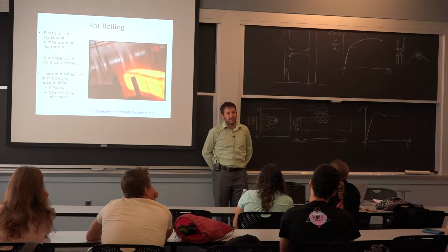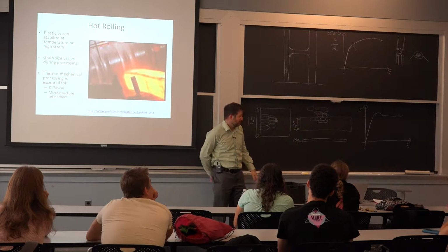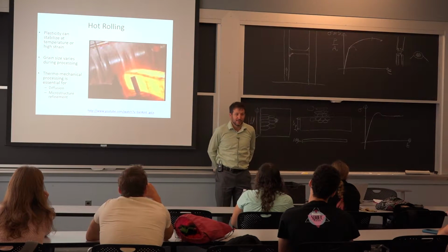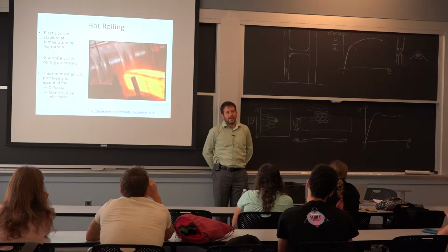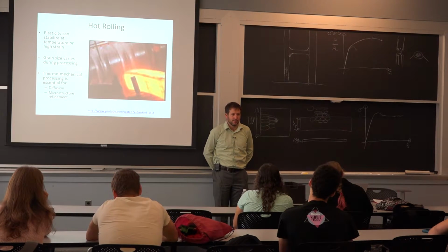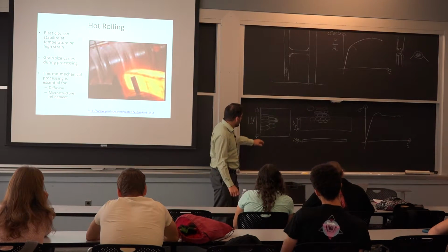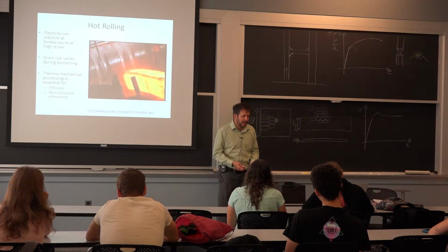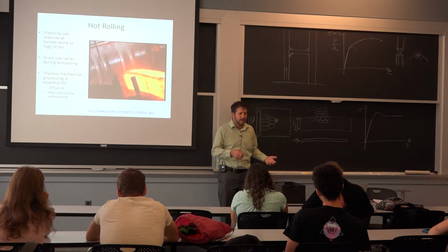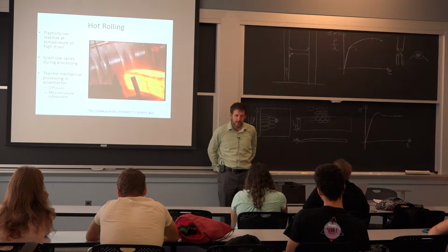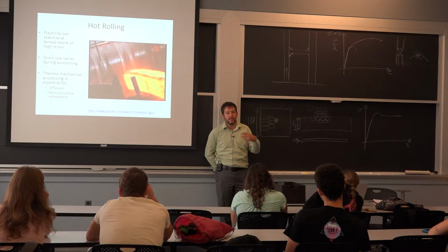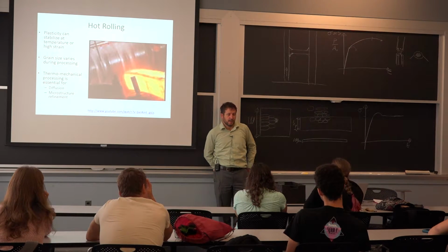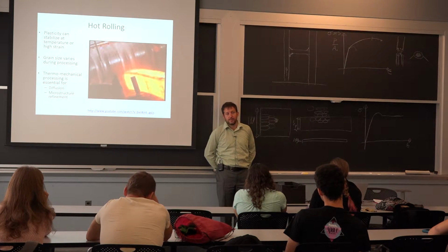One thing we haven't talked about, this is a little unfair because I'm talking about the metal, the grains, all that. Life is good. Inclusions. Inclusions are present in most engineering alloys. The reason is it'd be very expensive to make them without them. And in general, we can get by with inclusions. But the inclusions are essentially non-metallic. So say you have aluminum oxide, you have silicon oxides, all sorts of things that end up interacting. And some of them we generate. We add aluminum in the process to capture the oxygen, for example.